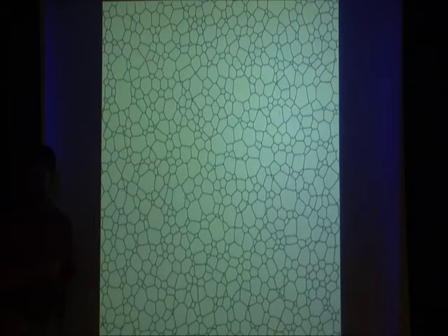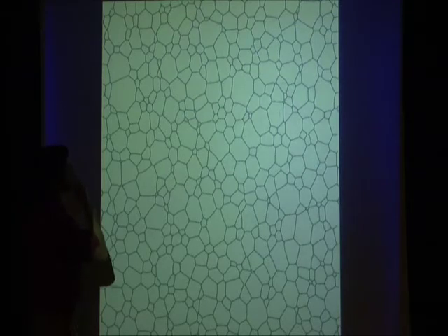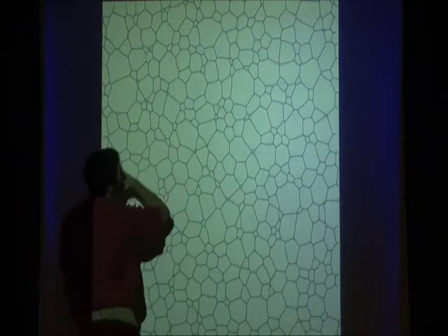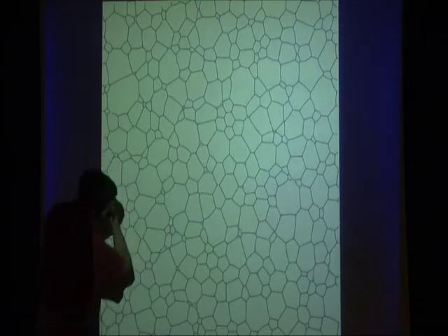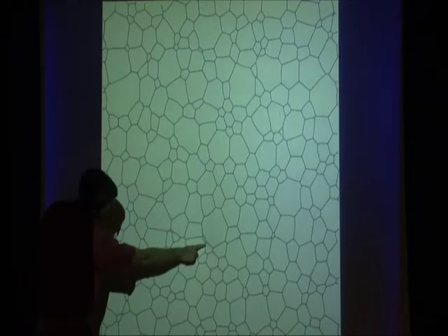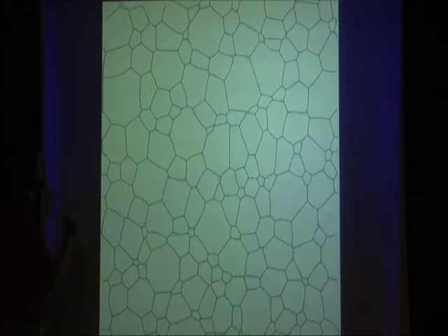The rate of change of the area is proportional to n minus 6. So if it's 6-sided, it stays fixed. 2-sided, they shrink the fastest of any possible grains. You'll occasionally see them, if you have something like, let me see, something like this. It'll pinch off there, and then sometimes it'll pinch off on the other side and have enough area left over, it'll be abandoned in the middle of an edge. They're extraordinarily hard to catch in this kind of picture. If you look at still images, you can pick them out with not too much difficulty. So that's one thing I want to point out.